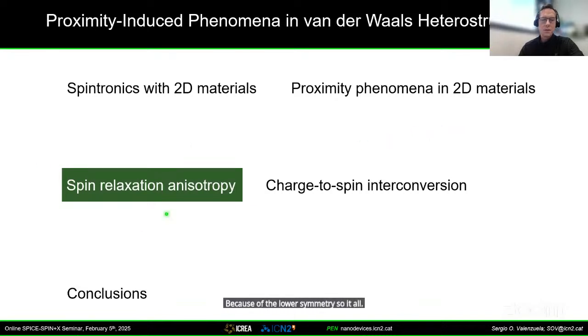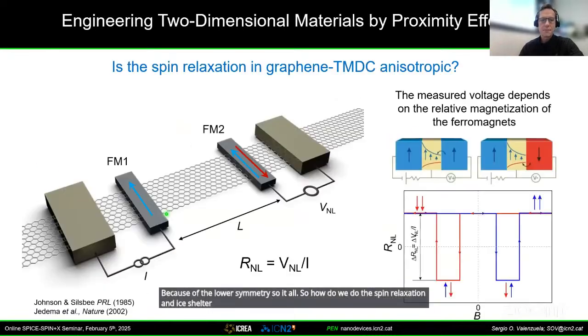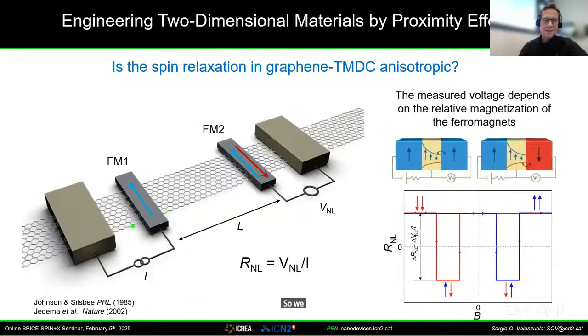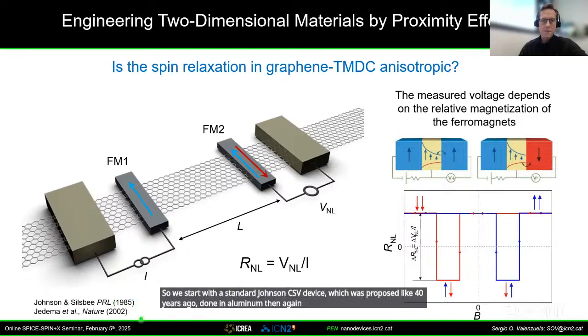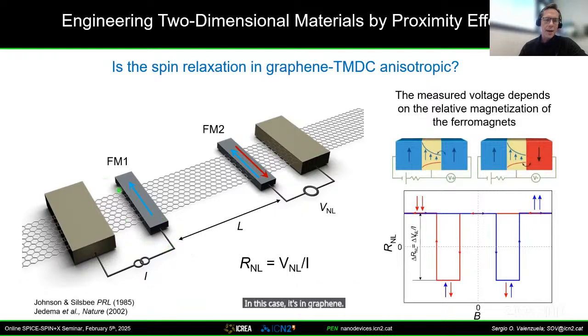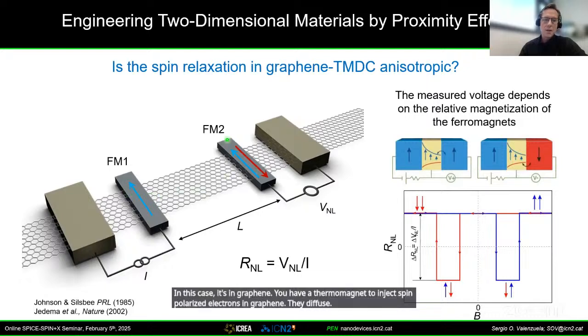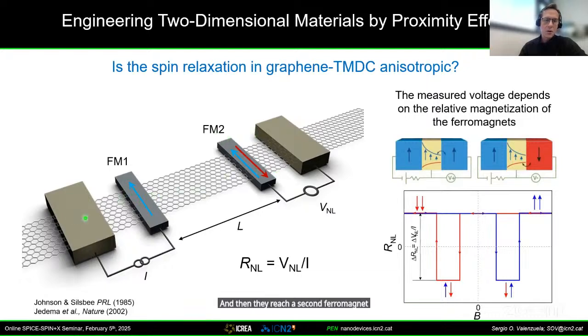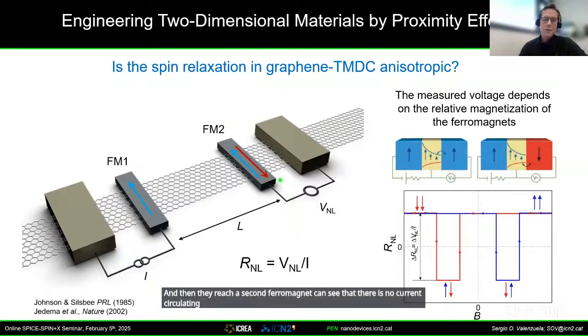So how do we do the spin relaxation and anisotropy? How do we investigate this? We start with a standard Johnson-Silsbee device, which was proposed like 40 years ago, done in aluminum, then again by the group of Van Wees, but in a much smaller volume, so they can observe the effects at room temperature. In this case, it's in graphene. You have a ferromagnet to inject spin polarized electrons in graphene. They diffuse, and then they reach a second ferromagnet. You can see that there's no current circulating here, and this second ferromagnet actually measures the electrochemical potential of the spin accumulation at this point.